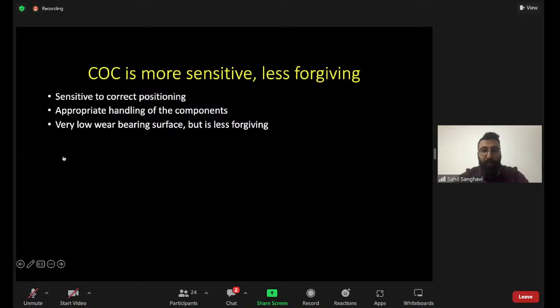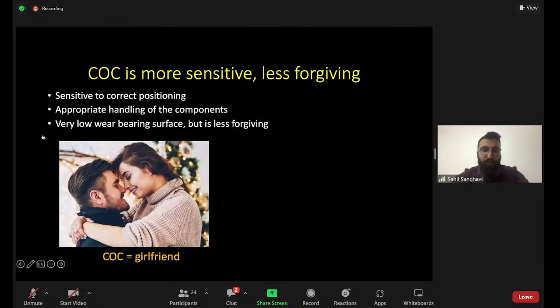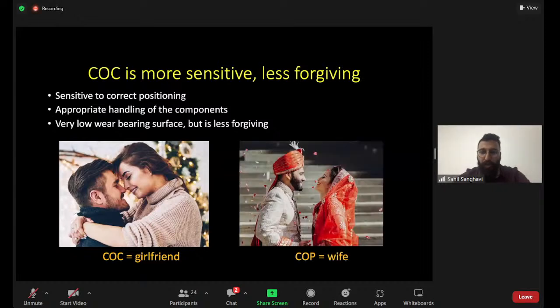So remember, ceramic on ceramic is more sensitive and less forgiving. It's sensitive to correct positioning. Even though it gives you a very low wear bearing surface, you must have appropriate component positioning. As my boss often jokes, ceramic on ceramic is like your girlfriend. If your positioning is not optimal, your girlfriend will leave you. But ceramic on polyethylene, on the other hand, is like your wife. If your wife is upset with you, she'll forgive you after a few days. In the same way, ceramic on polyethylene is a bit more forgiving as compared to ceramic on ceramic.